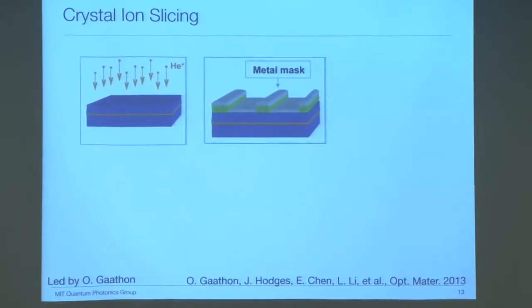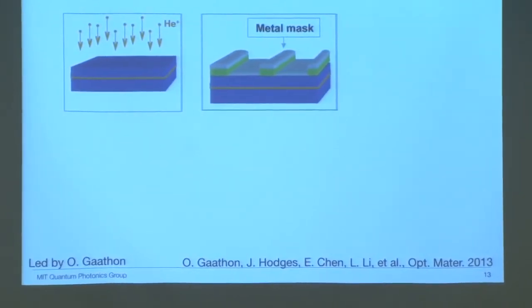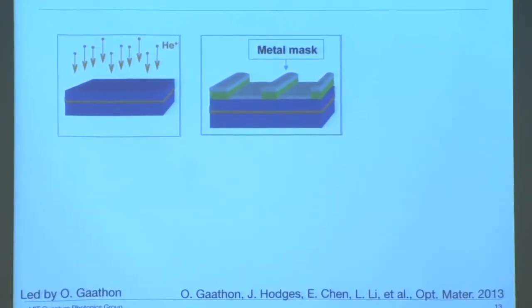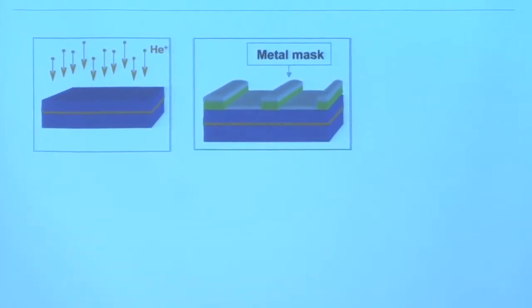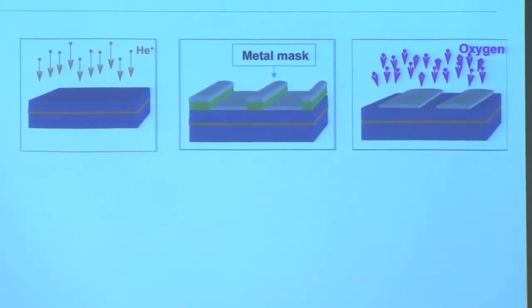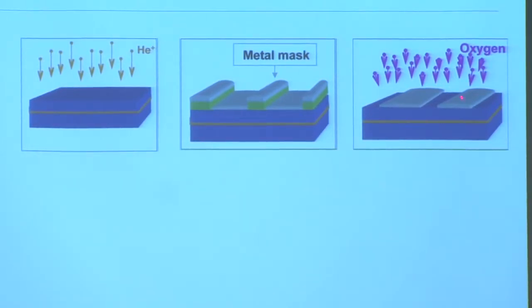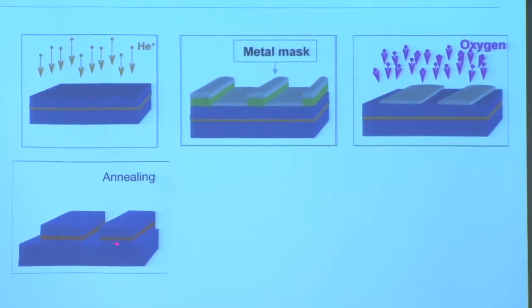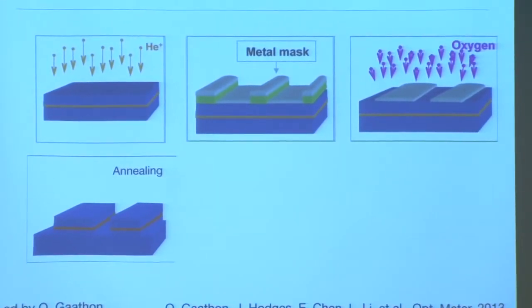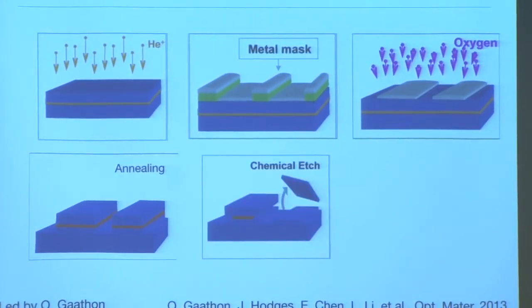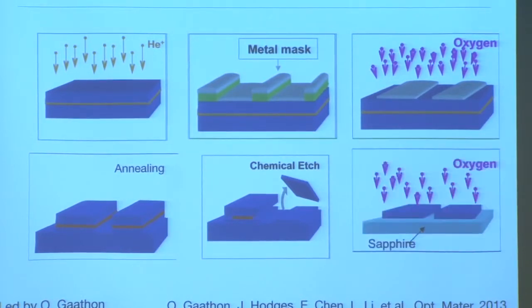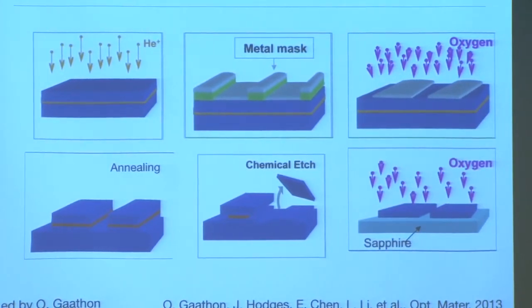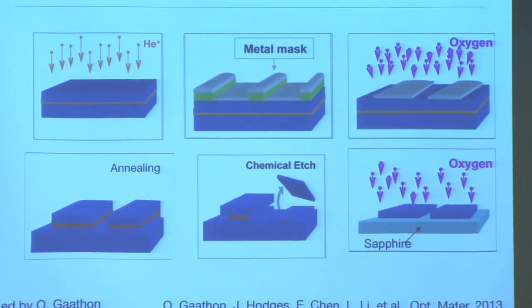And then we patterned squares by using optical lithography and metal lift-off techniques. And a subsequent oxygen plasma etching would transfer this metal mask into the diamond. After annealing, this heavily damaged layer turns to a graphitic layer, which can be easily removed by acid etching. And eventually, we are able to flip them over and use oxygen plasma to thin them down further and to achieve 200 nanometer desired thickness.